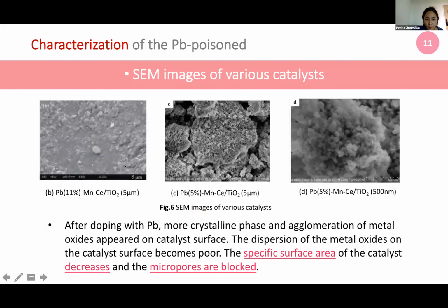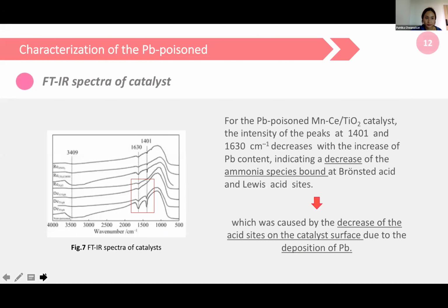After doping with Pb, more crystallization and accumulation of metal oxide appear on the catalyst surface. The dispersion of the metal oxide on the catalyst surface becomes poor. The specific surface area of the catalyst decreases and the micropores are blocked. This slide shows the FTIR spectra of the catalyst.